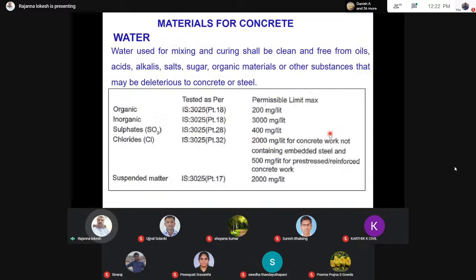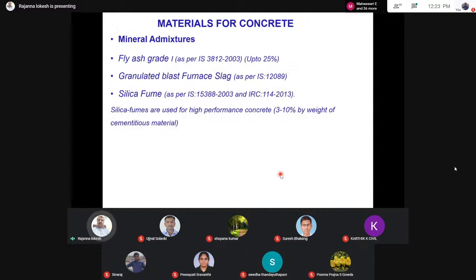So water that we use for concrete production should be potable. It should be clean. It should not have any acids, alkalines. These are the tests that should be carried out on the water that we use for concrete production. Then, as I mentioned, IRC also specifies the utilization of cementitious material by reducing the cement content. It can be fly ash up to 25%, GGBS, as well as silica fume. Silica fume is generally used around 3 to 10% to get high strength concrete.